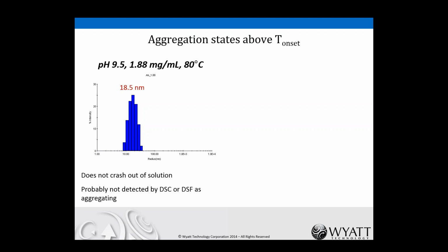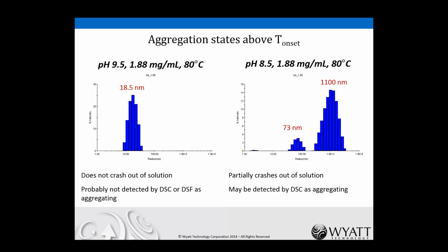If you were to look at the aggregation of this under this condition in a technique such as differential scanning calorimetry, perhaps even fluorimetry, you might not detect the aggregation because it doesn't crash out of solution, and so you really have no positive indication of what's happening. On the other hand, at a different pH, 8.5, the aggregation behavior is quite different, and here you see a population with an average RH of 73 nanometers and some really large particulates, about a micron in radius, and so this would actually be crashing out of solution, and this you would pick up with some other techniques. But the dynamic light scattering gives you all this information. It tells you about aggregation even without crashing out of solution, and the aggregation behavior, the rates of aggregation, and the different size distributions.